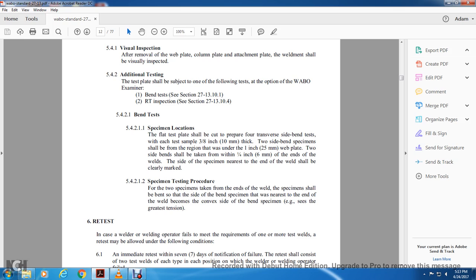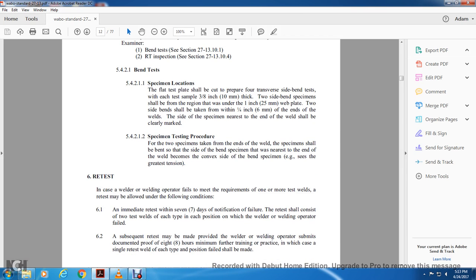Bending test, specimen location. The flat test plate shall be cut and prepared with 4 transverse side bend tests. For each test sample of 3/8 inch thickness, 2 side bend specimens shall be taken from the region under the web plate. 2 side bend specimens shall be taken from within 1/4 inch of the end of the weld. The side of the specimen near the end of the weld shall be clearly marked.